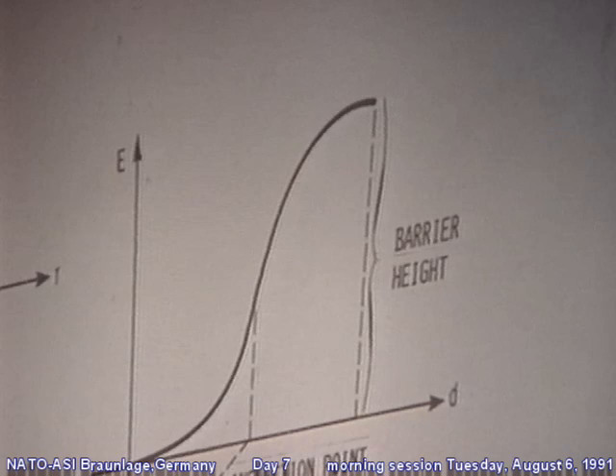When you do these kinds of things, you get curves that look like this — energy versus separation. If this were a bulk process, that well depth would be the cohesive energy. If it were separating two surfaces, it would be the surface energy. In this region you have an attractive force, and if you try to make it go into the repulsive region, you get a very strong repulsion. The derivative of that curve is the force or the stress. If you're sliding one half space over another, you see a similar thing — you push, you run into some sort of energy barrier, and again if you take a derivative, you have some maximum force involved in that process.